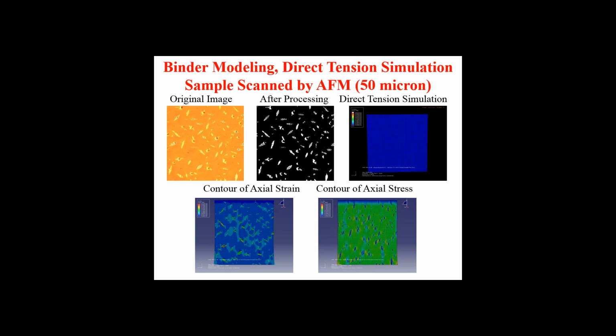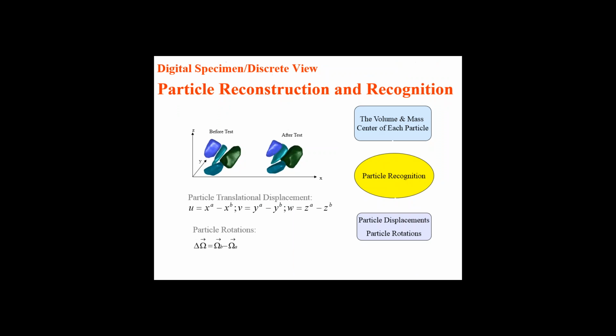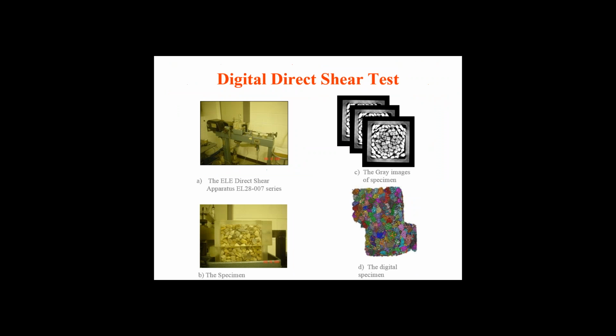And then this one, extended to the binder, and you see the wax distribution, and this wax would affect the binder properties as well. Using a similar approach, you can model the behavior or the material performance if you contain different types of wax contents in there. Particle approach, reconstruction, recognition. We did this digital specimen along with this DEM approach.